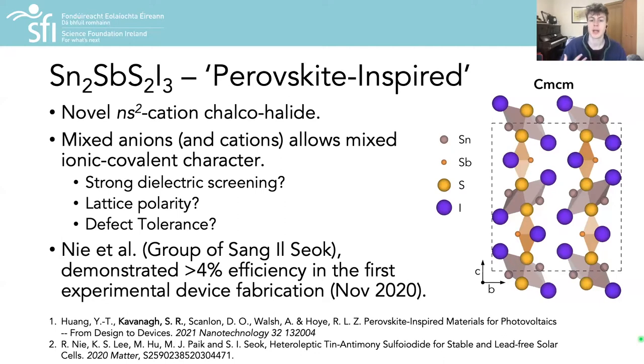Strong dielectric screening also promotes lattice polarity and other properties associated with defect tolerance. So all these properties are promising signs for the potential application of these materials in optoelectronic devices, but does it actually translate into device performance here? Well, recent work published at the end of 2020 by Nie et al. in the group of Sang Il Seok certainly indicates the potential of this material class, demonstrating over 4% efficiencies in solution-processed devices alongside excellent air, water, and photostability.